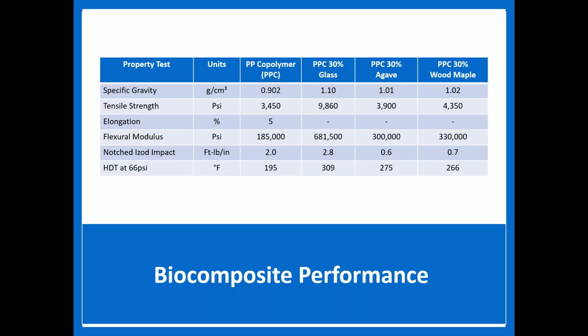Okay, biocomposite performance. So as I mentioned, this would be, we put in a bio-based kind of almost like a reinforcement or a filler. So in this table, I included both copolymer unfilled, so you can kind of see where it's normally performing, and then a glass-filled product, because I do mention it does give you an improvement in stiffness and strength, just not all the way to that of the performance of glass. So you'll see 30% agave, 30% wood maple. You can see specific gravity went up because you're putting stuff in it, but you can see that your tensile strength and your modulus both went up, just not all the way to glass.